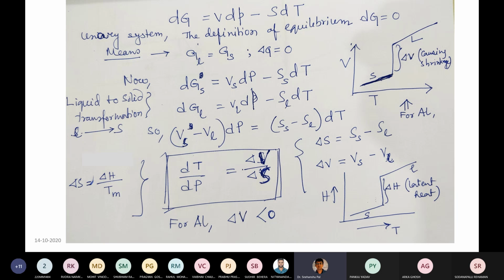So if you are talking about aluminium, delta V equals, which one is having higher volume? Liquid is having higher volume. So delta V is always negative, and in the same way liquid has higher entropy, so delta S is also negative. So from liquid to solid, there is a latent heat. Delta H change will be there, and that is actually latent heat. What is latent heat? The heat or enthalpy required for the transformation of one state to another state, but it does not contribute towards an increase or decrease in temperature. So there is no change in temperature, but it actually helps the transformation of one state to another state.